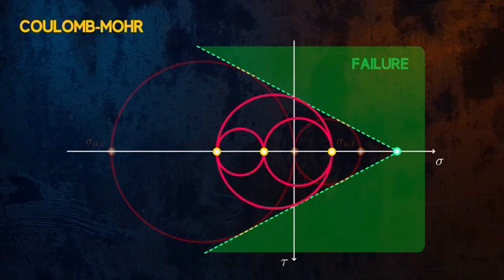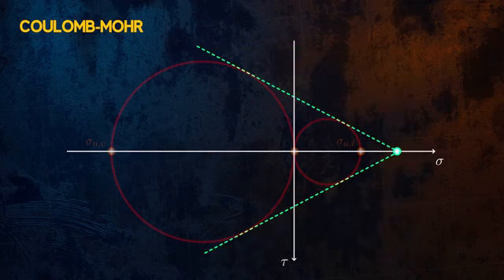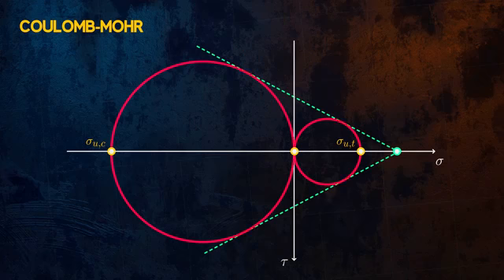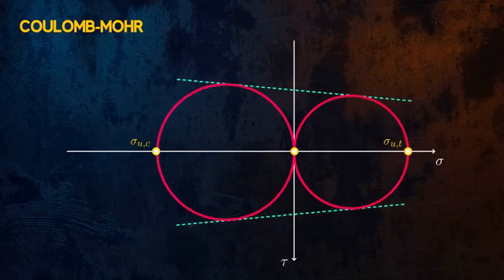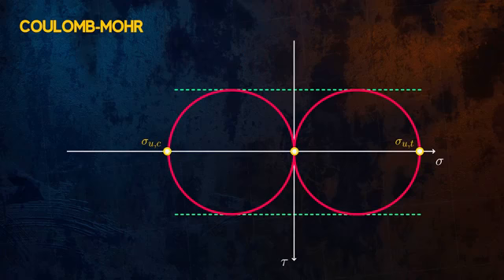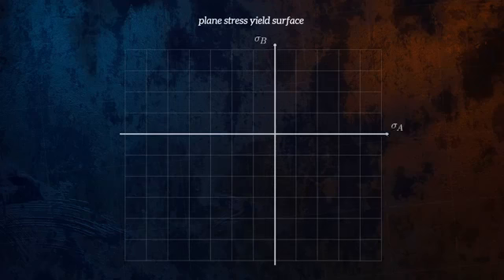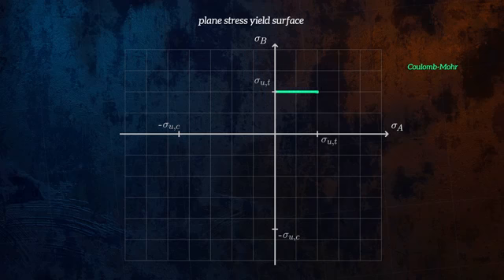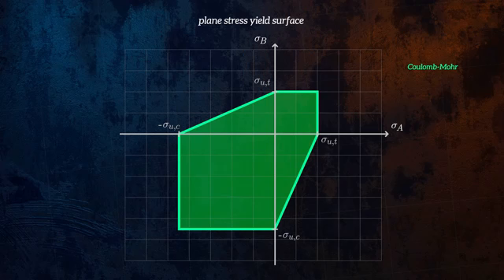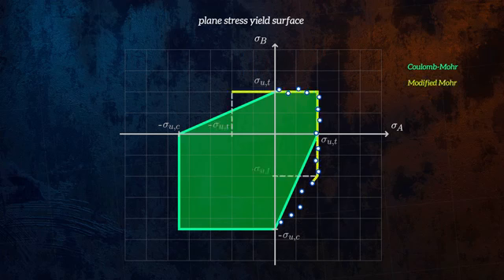The Tresca yield criterion we saw earlier is actually a special case of the Coulomb-Mohr failure theory, where we have the same material properties in tension and in compression. The plane stress failure surface for Coulomb-Mohr theory looks like this. As you can see, it doesn't agree particularly well with experimental data in the bottom right quadrant. Modified Mohr theory is a slight variation on the theory which better fits experimental data. It is one of the preferred general failure theories for brittle materials.